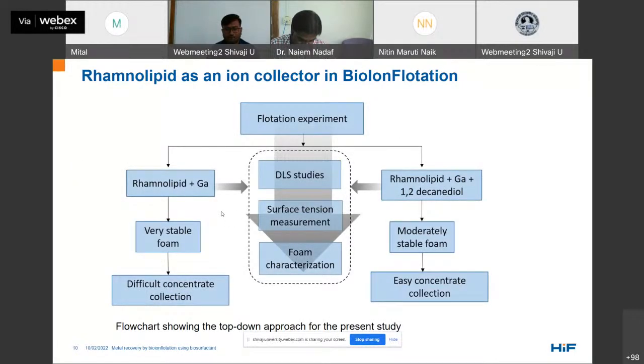So this study was carried out in a top-down approach as depicted in this flow chart. During the first flotation experiments, it was observed that mixing of rhamnolipid and gallium resulted in a colloidal solution. Further, it was seen that the collection of concentrates during flotation was difficult due to the high foam stability of rhamnolipid. So we added 1,2-decanediol, which is a common non-ionic frother, and it imparted a little instability to this foam and also eased the collection of flotation concentrates.